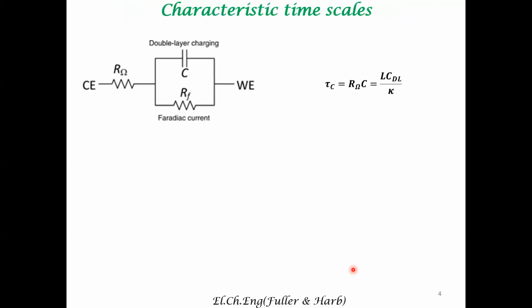So let us compare this time constant, that is the capacitive time constant, where we have substituted for resistance and obtained this formula. This is the conductivity and characteristic length of the particular system we are looking at. So we want to compare this time constant with certain other processes that can occur at the electrode-electrolyte surface. There can be many processes, but we will just look at one particular process, which is the diffusive process. In an earlier lecture, we had looked at the characteristic diffusion length scale, which goes as the square root of diffusion coefficient times time. We had done this when we had looked at the Cottrell equation. So from here, we can get the